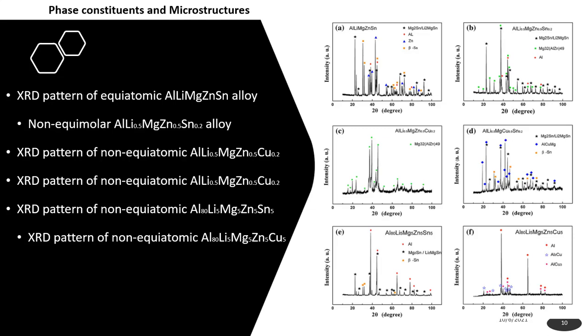So these authors, Zhang and team, in order to identify the microstructure and the crystal structure of this particular equiatomic alloy, combined the XRD analysis with SEM and EDS analysis, and they were able to determine the crystal structure of this alloy to be an FCC solid solution.